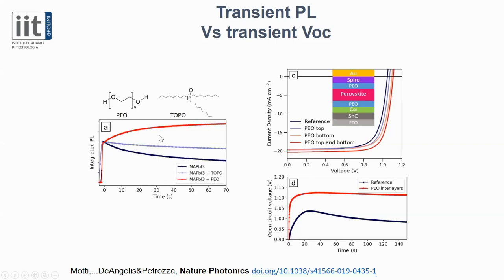We passivate the perovskite with a polyethylene oxide layer, which has technological relevance. It is also good for fabrication, easy to use in the fabrication of solar cells. And you can see on the right, we also fabricated a solar cell, a few years ago, with about 20% power conversion efficiency. And you can see that the passivation of the perovskite surface not only improves the VOC of the solar cells, but also stabilizes the open circuit voltage over time, as we can see in the photoluminescence.